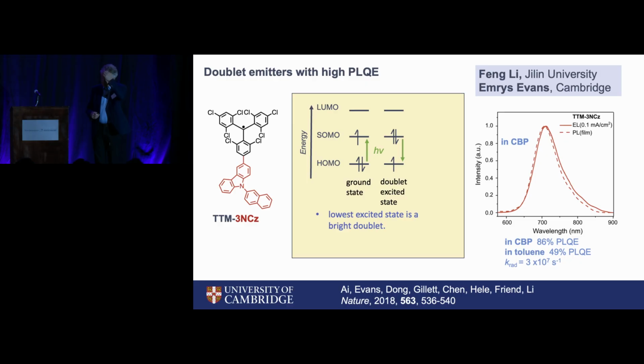But this bucks that trend. So in the middle, the panel in yellow shows on the left the ground state, where we have 2 electrons in the highest occupied molecular orbital, which is the lone pair-centered orbital on the carbazole. And then we have the SOMO, the singly occupied molecular orbital for the radical at the top. And the optical transition goes from left to right. We simply go up and down within the doublet manifold, and it's bright.